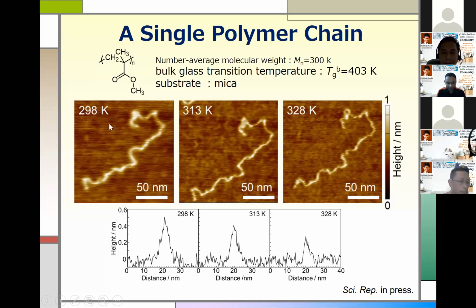And then we elevated the temperature from room temperature to 313K. And then this shape became clearer. And then we went further, like 328K. And this image was actually less clear. And why is that? Because with increased temperature, molecular motion became activated. That is why we could see this kind of a difference. But from here to here, conformation was changed from loop conformation to train conformation.